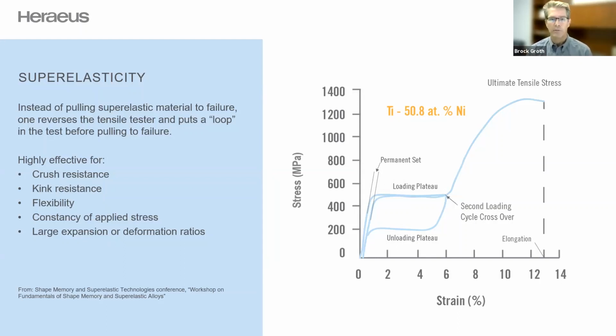This is often specified as something like 0.25% after 6% strain, or 0.5% after 8% strain, something in that order. But there is a tiny bit of permanent set, and this loop between the loading plateau and the unloading plateau is the superelastic loop. That's where the so-called magic of superelasticity takes place. Again, this superelastic loop is great for all the things mentioned on the left: crush resistance, kink resistance, flexibility.